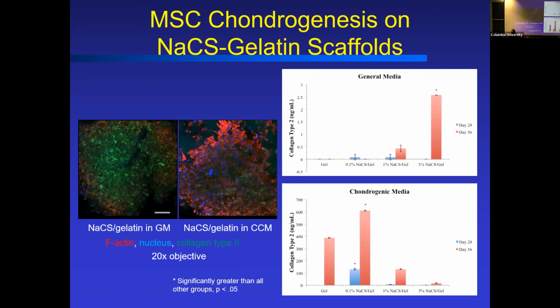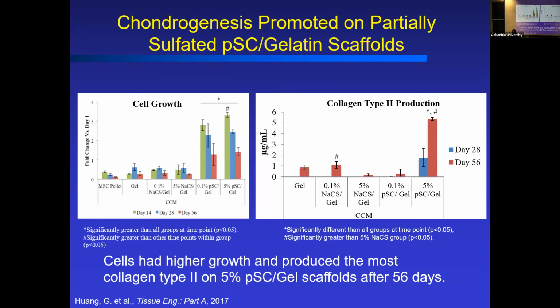If we put them on the scaffolds now, the scaffolds that have that fully sulfated cellulose, we see a similar expression of these cartilage markers, high expression of collagen type 2, which is what you want to see. And you don't need much of it. That fully sulfated cellulose, only about 0.1 weight percent of that needs to be in those fibers in order to give you a high amount of collagen type 2 production out of those cells. Even with or without the presence of growth factor, that TGF beta in the media, we also see this driving of chondrogenesis where the cells are expressing collagen type 2.